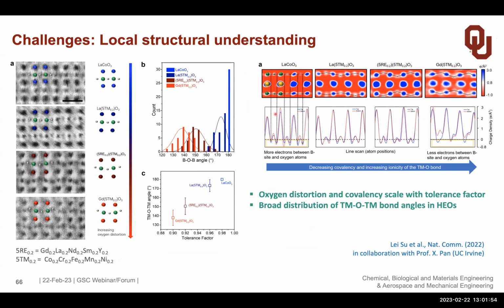And what they can do using this advanced microscopy is look for the bond angle between the transition metal ions. And this is decisive also for the magnetic properties. So in this study, we could correlate this bond angle modification, which you can follow here, to the magnetic property of the material. And this is, of course, very interesting because you can correlate something which happens between 3 ions in the system to the macroscopic property of the material.